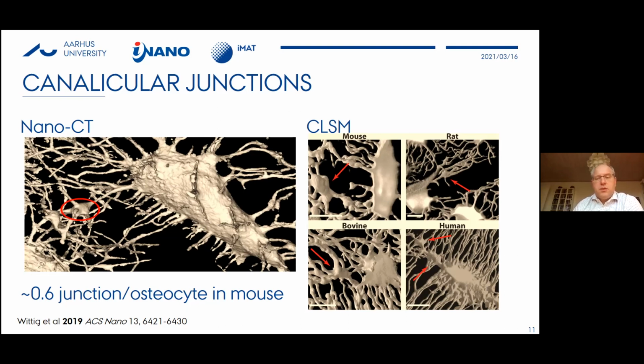To test if this is really biologically in contact with the fluid dynamics of the bone, we used confocal laser scanning microscopy. We placed pieces of bone in a solution with dyes, and the dyes then infuse into the void space of the bone, allowing us to see which parts are connected to the network.